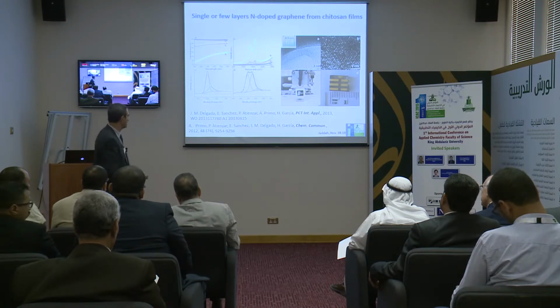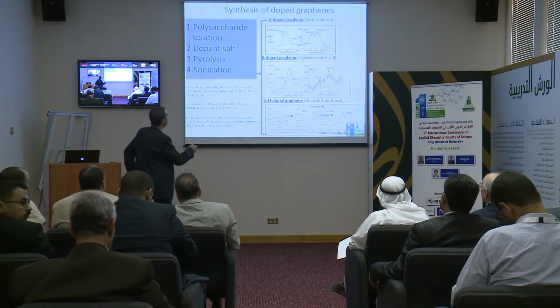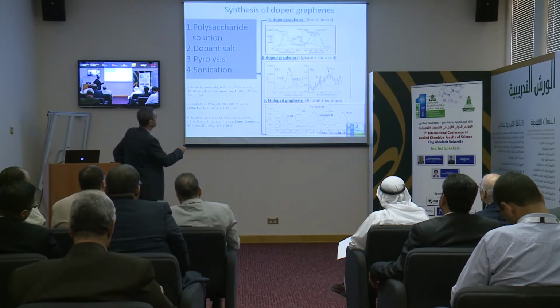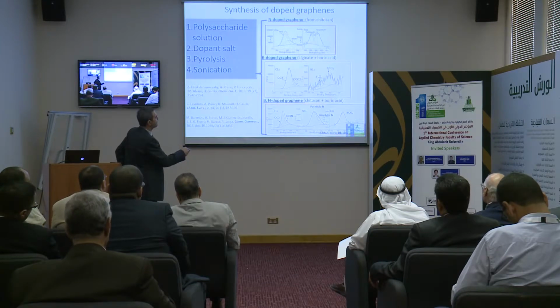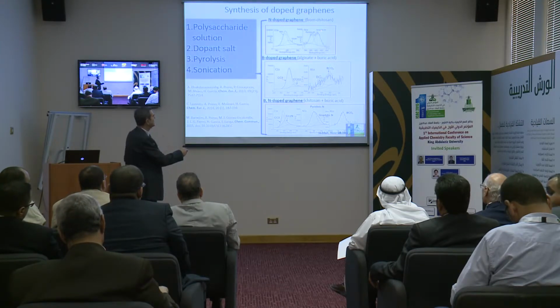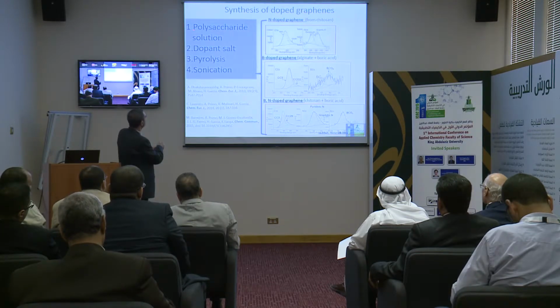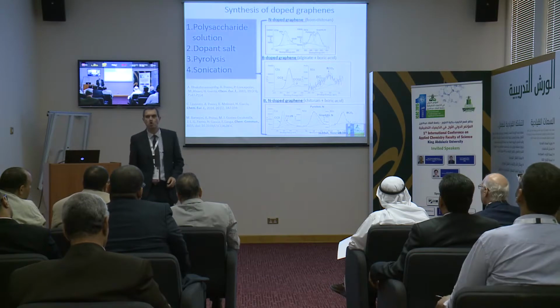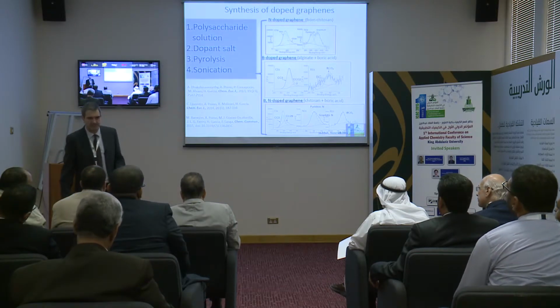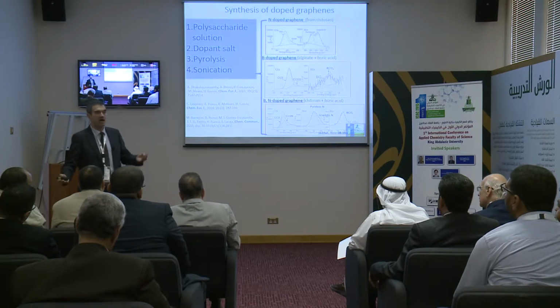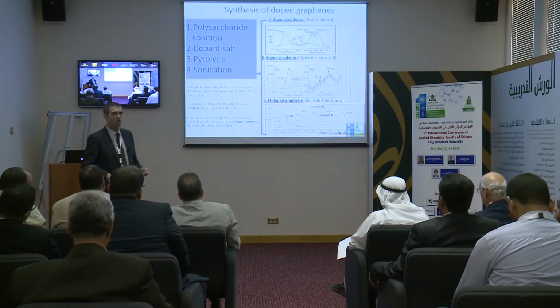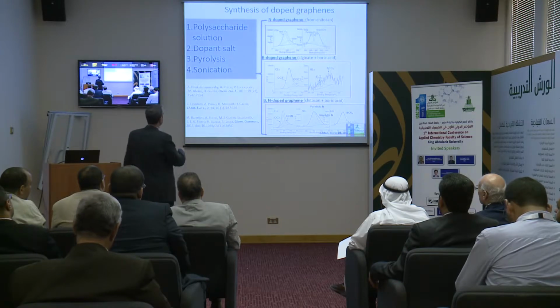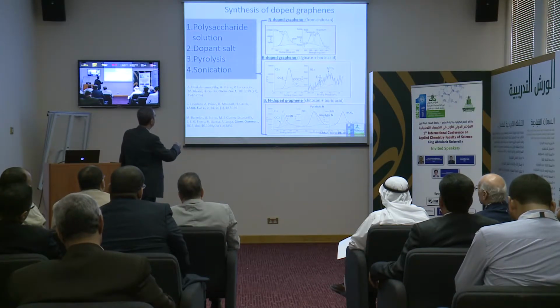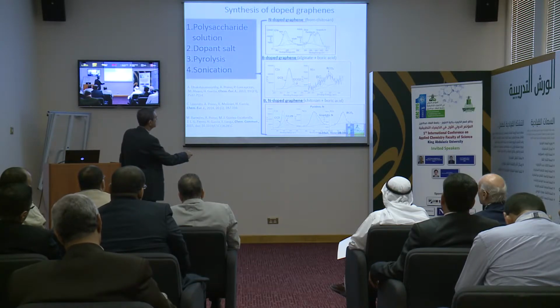with defects for catalysis. So doped graphene, we can dope with other heteroatoms, for instance, besides nitrogen, that is just prepared by pyrolyzing chitosan that contains carbon and nitrogen. We can also produce graphene doped with boron. In this case, the procedure consists in forming a polysaccharide solution, and then we make the ester, because most of the polysaccharides form inorganic esters. For instance, the reaction between boric acid and the polysaccharide forms the borate. This is very well known in sugar chemistry. So we form here the ester, and then by pyrolysis what we obtain is a graphene that contains some boron.